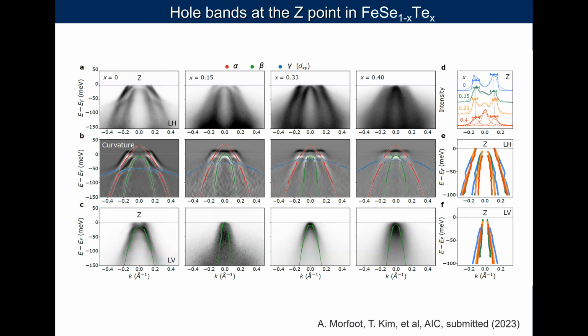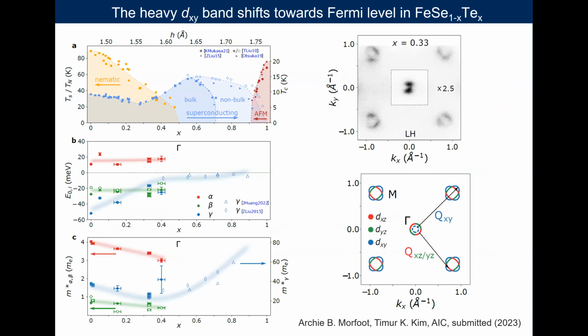the Fermi level. And if we put all this data together and model our dispersions using the 3-band model, we can extract the information about the shifting of this dxy band and the effective masses associated with it. And interestingly, in the tellurium series, nematicity is suppressed, but then superconductivity shoots up again.